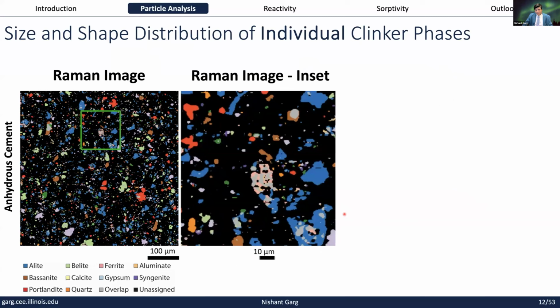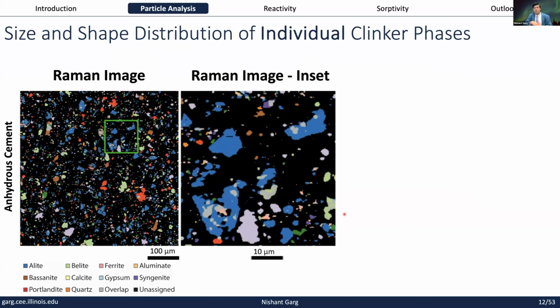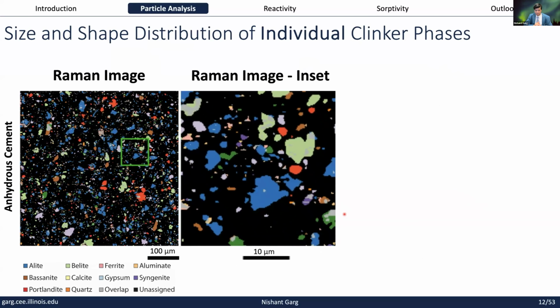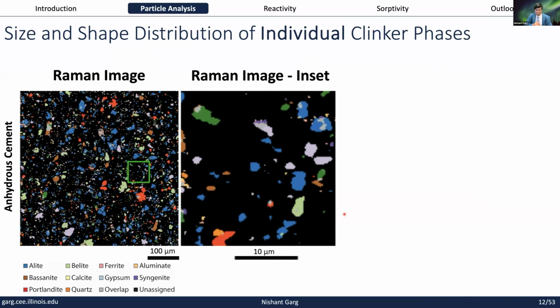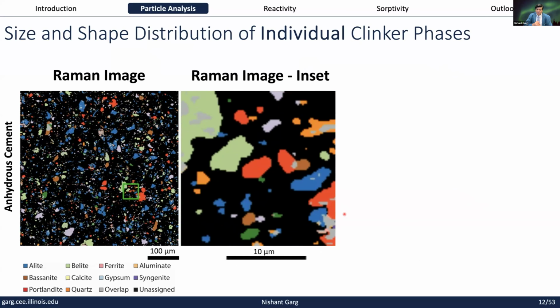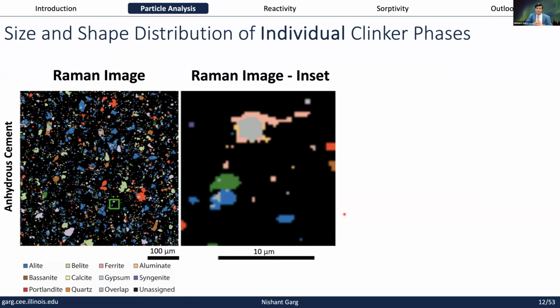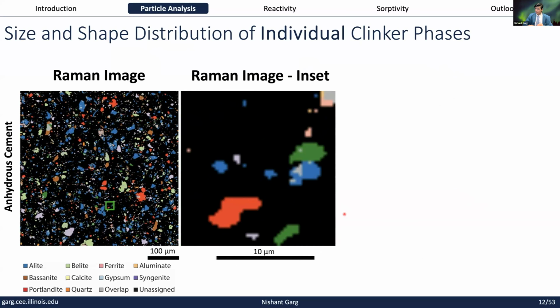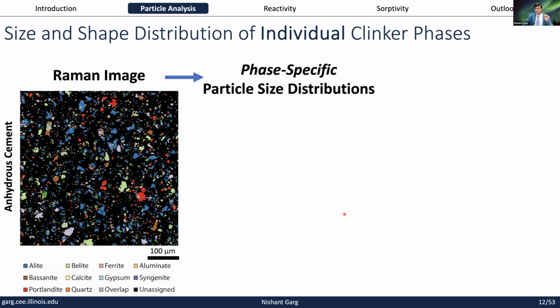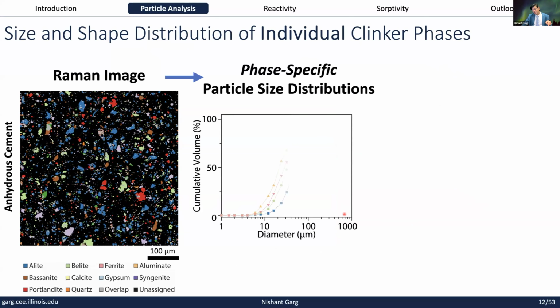Then one of the things we have been very interested in is, can we take one step further? Can we look at the size and the shape distribution of some of these clinker phases? Because we have these high resolution scans, can we then obtain what we call the phase specific particle size distribution? So instead of having one global PSD, we can get a PSD for every single component within that system.